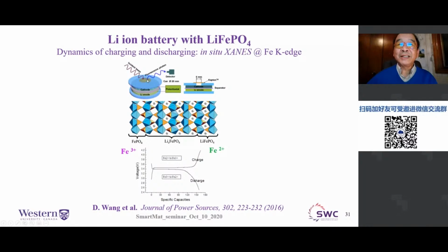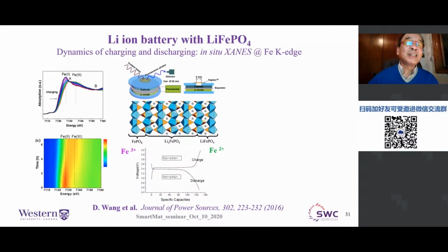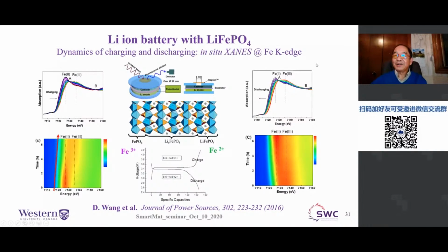The idea is that we look at the system during charge and discharge. During charging, for example, you can do a series of scans, and you can see the E0 moving as we charge from iron 2 to iron 3. This is just another way of displaying it, where you can clearly see how the E0 shifts as you charge. Similarly, you can also do the discharging, and of course you can see you're going back from iron 3 to iron 2 as you discharge.